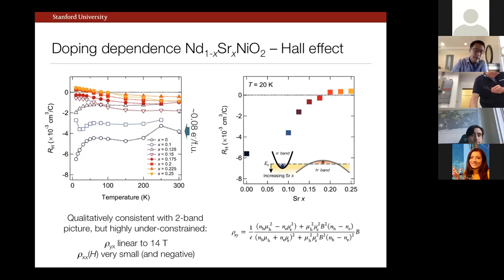On the other hand, as we then think we're doing hole doping, the Hall coefficient remains negative but gets smaller and smaller. So this is highly inconsistent with this picture. This would be as if we're making it a higher and higher electron density. The second thing that is immediately apparent, both as a function of doping and as a function of temperature, is this very smooth crossing of zero in terms of the sign of the Hall coefficient.